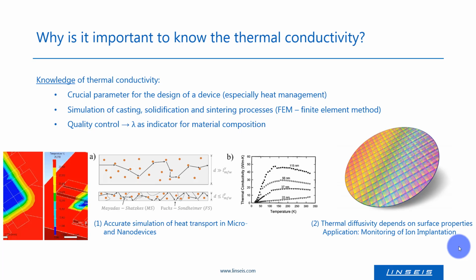Another example is that the thermal conductivity can be used for quality control. The thermal conductivity can be an indicator for the material composition or defect structures. For example, the result of surface ion implantation on a wafer can be monitored by using a TF-LFA, by mapping the thermal diffusivity of the surface area of the wafer.